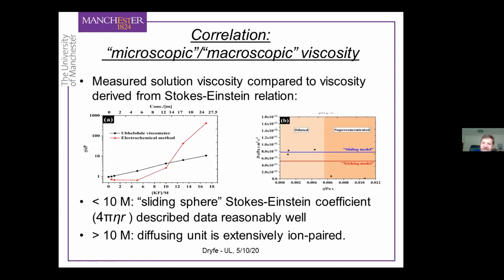And one reason, I think, which I've alluded to already, is that the molecule, because we're using a charged redox active species, becomes heavily ion paired at these high electrolyte concentrations. So the thing that's actually moving through the solution is much larger than at the low concentrations. So this is an artifact of the ion pairing, that we're seeing this massive change in the apparent local viscosity at these high concentrations.